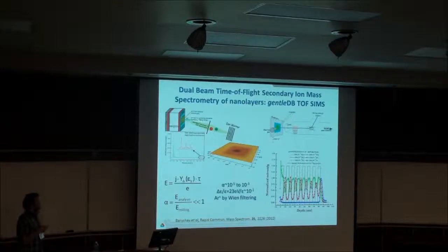We repeat these cycles: one for milling, and then we reveal the subsurface, and then we use a pulsed argon plus ion beam to probe this revealed surface. Under this pulsed ion beam, a plume of secondary ions goes to our time-of-flight mass spectrometer, and then we generate this pattern of mass spectrum, showing intensity versus mass.